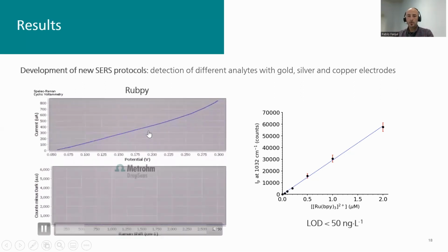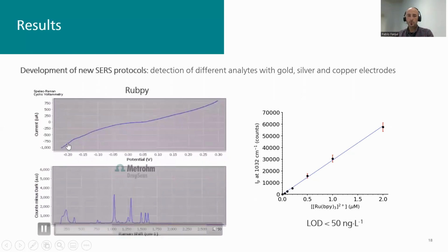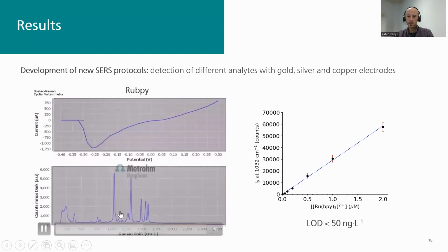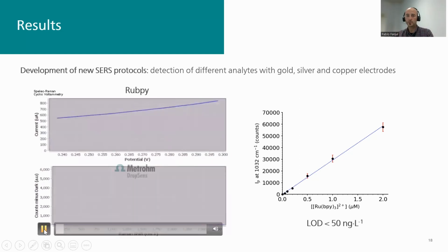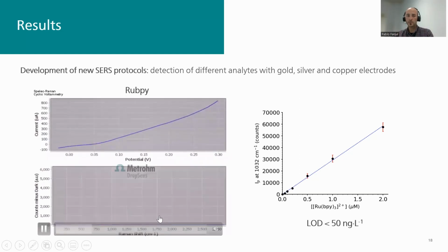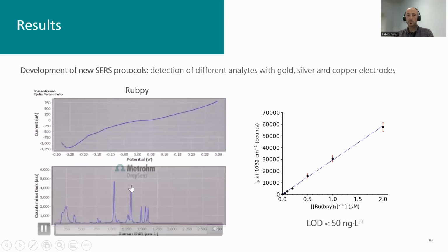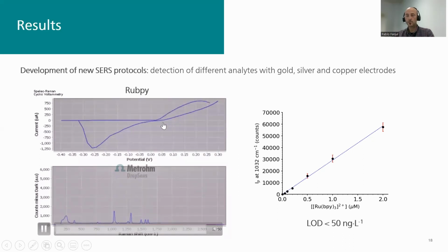Okay, so here we start to reduce the silver, we generate the particles, and then we can see the Raman spectra. And even in the backward scan, when we oxidize again the silver particles, we almost lose all the Raman spectra. It's not completely lost, but you can see clearly how the SERS effect is obtained mainly at these negative potentials, and then how it is going down.